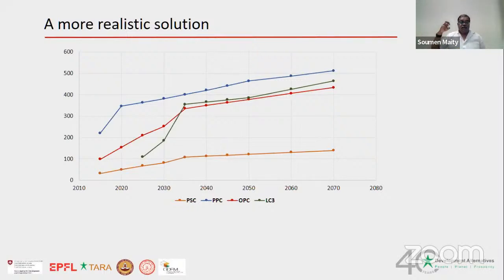Fly ash-based cements will be there. LC3 will replace some amount of OPC, and in certain cases it will be a preferred choice of cement companies instead of PPC. So these are the growth projections that we say. And if that is the situation, then we will be contributing around 10 to 15% of the NDC, the targets that the government has set for itself.